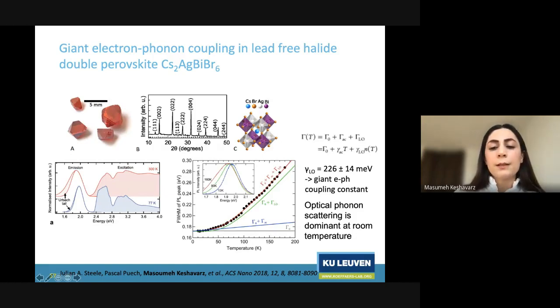For example, one can see which one is the dominant scattering mechanism by looking at the contribution of each of these terms. And also one can access the exact coupling constant, the electron-phonon coupling constant. What we could conclude from these measurements was that the optical phonon coupling constant for this material is more than 200 milli-electron volt, which is much, much larger compared to the single perovskites, which are in the range of 50 to 70 milli-electron volt.